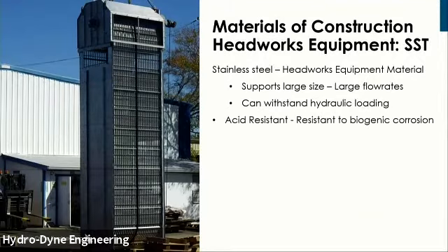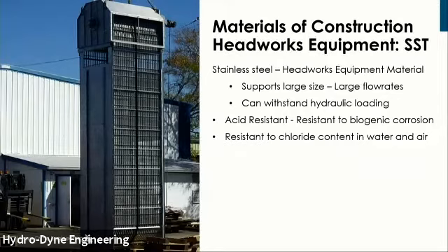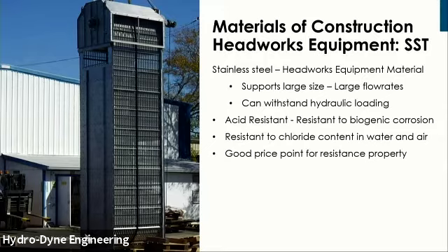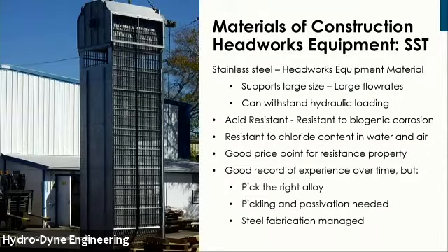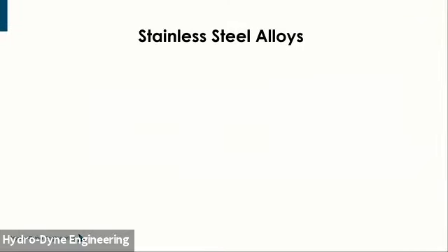Stainless is acid resistant, and that means it's resistant to biogenic corrosion as that occurs around the headworks. It's resistant to chloride content to a certain extent. Generally has a good price point and a good record over time, but there are a couple caveats. One must pick the right alloy for the right application. Pickling and passivation are needed in the stainless steel fabrication process, and the steel fabrication has got to be managed. We'll talk about that a little bit more.